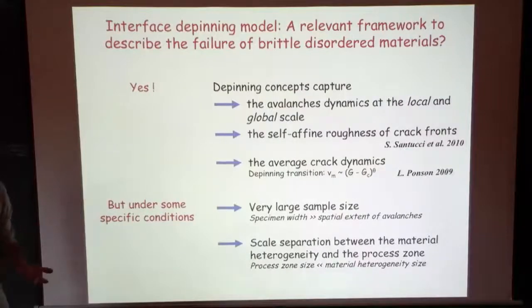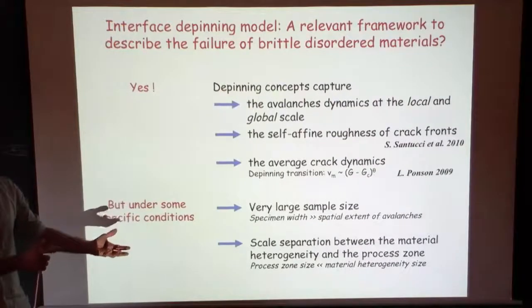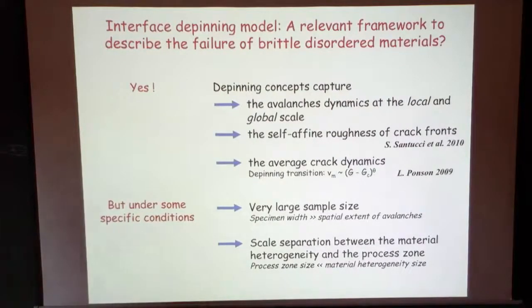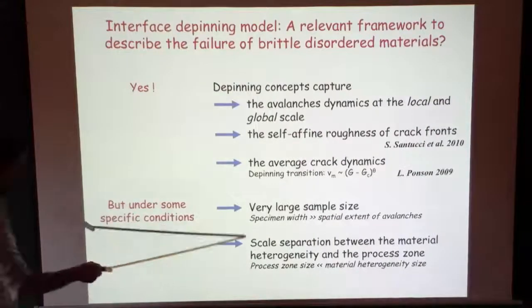So to have this scale separation, the best way I can think of is to build your own material where you artificially plug in a sufficiently large length scale, a grain size, made of glass beads, much larger than the natural length scale in your material. Or the idea of the heterogeneous adhesive, where we artificially put defects at a millimeter scale, much larger than the scale of dissipation in this adhesive, which is the micrometer scale. So I would say it's also a big restriction.